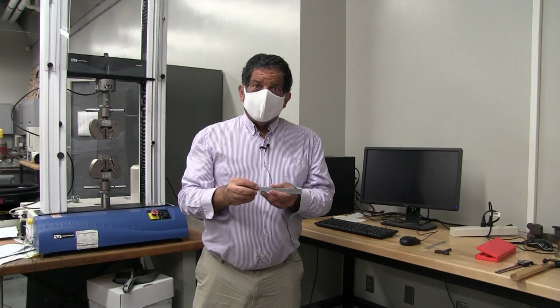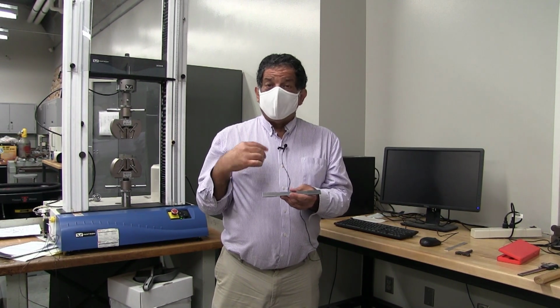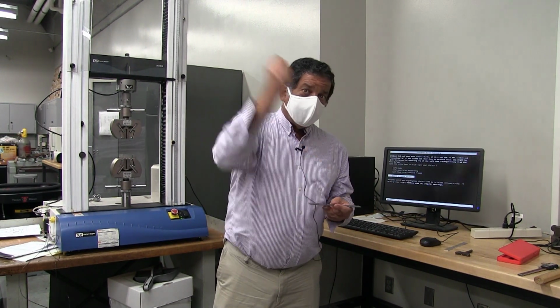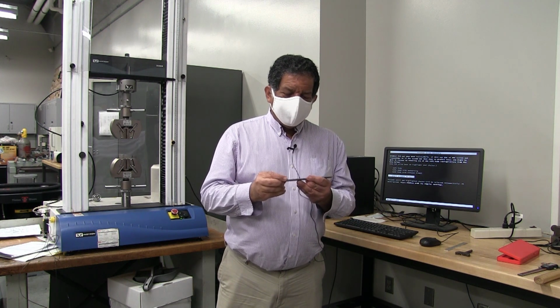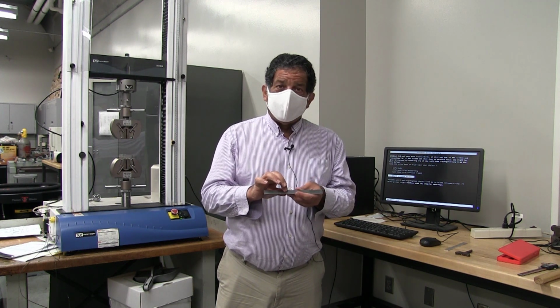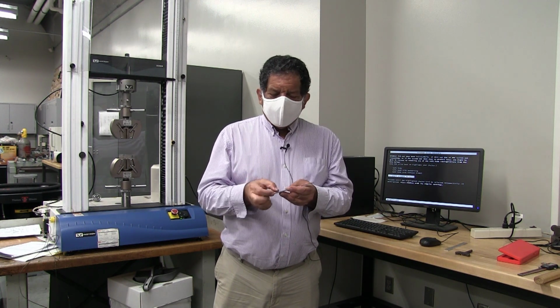Now, what you want to do is make sure that the indentations are deep enough so that you can definitely see them, but you don't want to whack down on the specimen, because if you put too deep of an indentation on there, then you're creating a large enough stress concentration that that'll change the results of your test.